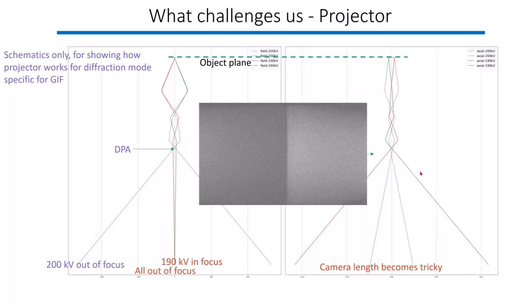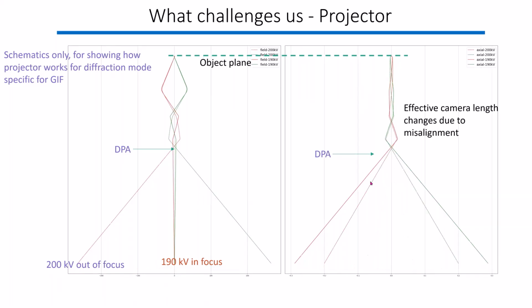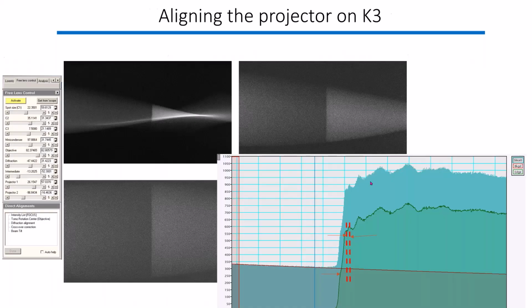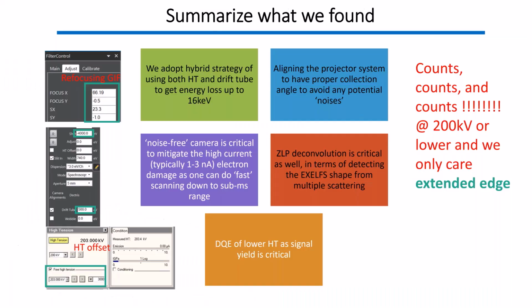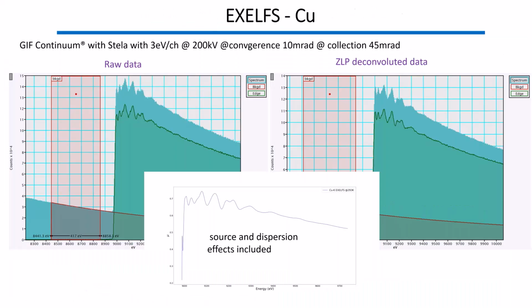The next question was, are the oscillations in the fine structure or the extended edge more pronounced in the deeper edges? I guess as the S states become more tightly bound, as you go higher in energy loss, compared to the K edges that are below 2 keV. Have you looked at or done any analysis on any edges that were less than 2 keV in energy, or mostly stuck with the highest energy edges?